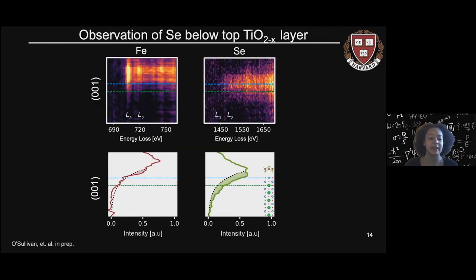So similarly, we conduct the same analysis for two elements of interest in particular, iron and selenium. You'll note that here I've simply put our line cuts and our energy loss maps. And with our line cuts, you'll see that the iron resides well above the top layer of titanium and strontium, as we would expect in our monolayer of iron selenide. However, our selenium resides slightly lower, shifted further down with a significant amount of selenium signal below the top layer of titanium and below the top layer of strontium.